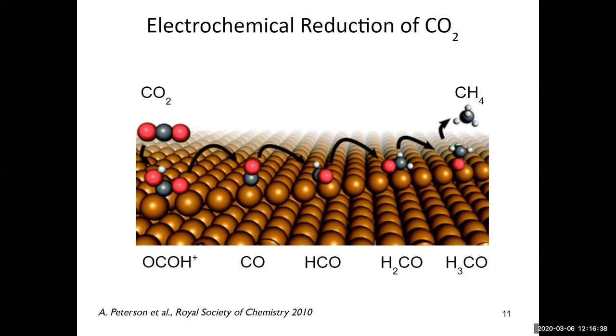Relatively simple pathway. When you do the kinetics, what you see is that the CO to CHO step is usually the rate limiting one. And so these two intermediates are interesting. And if you really examine this transition state, it is a little bit closer to the CO than it is to the CHO. And so this really implicates the CO adsorption energy in the overall kinetics of this pathway. So an obvious thing to do is to say, does CO adsorption correlate with what people know experimentally on CO2 reduction?